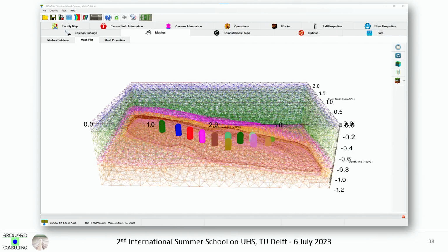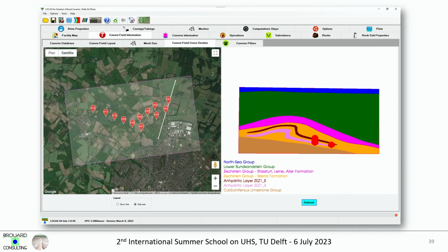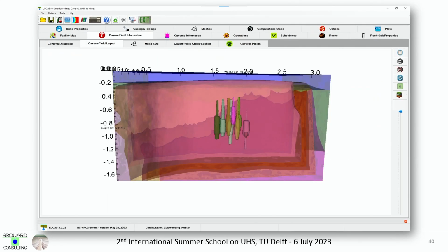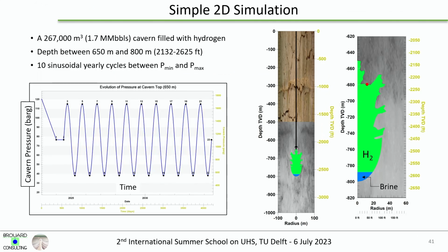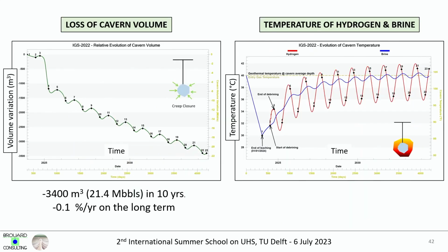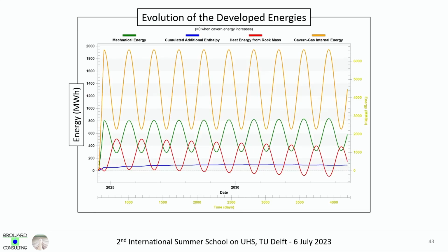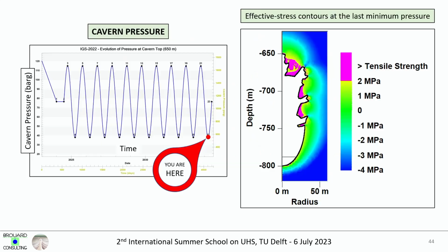Just a few slides to show what it looks like. You see the 3D version. This is, for instance, Zuidwending salt caverns with the actual shapes of the caverns. I show you an example of a 2D simulation of a hydrogen cavern with seasonal cycling, 10 years of cycling like this. You can calculate the loss of volume and the increase of the brine and hydrogen temperature, and all the developed energies.